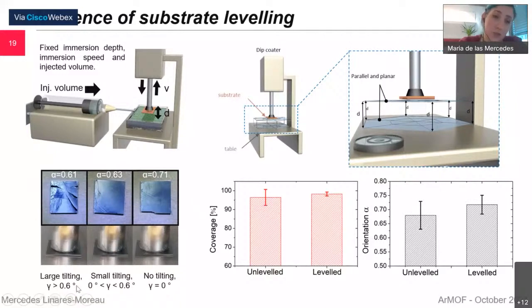For angles above 0.6, we have cracks and bubbles. And then even for very small tilting, between 0 and 0.6, which was hard to see, we would get homogeneous coatings. But if you look at the orientation, actually, the orientation was worse than when we finally used a perfectly leveled, 0-degree tilting sample holder, which requires a tilting precision below 200 microns. So initially, we didn't know that this kind of precision was needed. This was the first challenge that we could overcome.